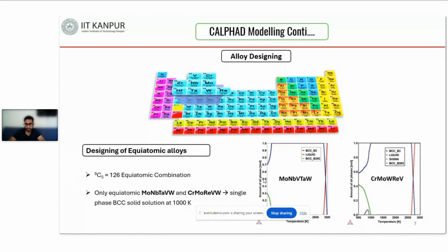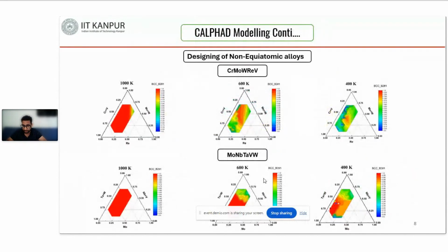So we jump to the non-equiatomic alloy compositions, in search of an alloy which shows a large thermal stability over a wide temperature range. Since we got these two equiatomic alloys showing good results, we tested the non-equiatomic compositions of these alloys. What does non-equiatomic mean? Earlier, in the equiatomic case, all the principal elements had equal chemical composition. Now we are varying the composition of each individual element from 5% to 35% and generating different alloys. In this way, when varying the composition of each element, we got 1451 alloys from each equiatomic alloy.